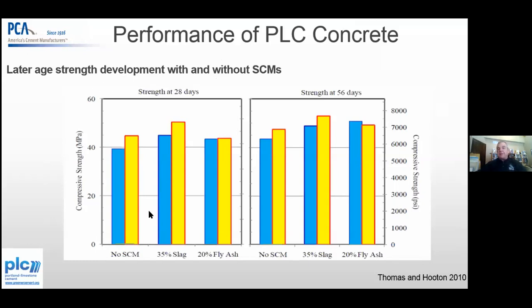And at later ages, the same thing happens. You've got equal performance, same for no SCMs, 35% slag, 20% fly ash, and at 56 days, the same thing. Increased performance for Portland limestone cements, and for the 20% fly ash, just slightly diminished in this particular one at 56 days.